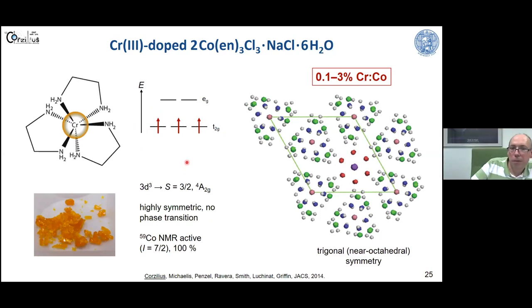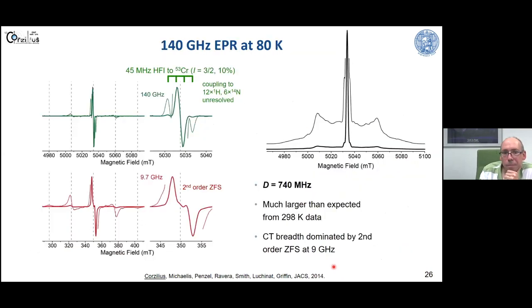And due to the significant ligand field, the excitation energy into an excited state is rather large. So we have a more or less isotropic g factor. However, we have a small deviation of octahedral symmetry into a trigonal distortion. This introduces some zero-field splitting, because zero-field splitting is really sensitive. Even without strong spin-orbit coupling, we have this kind of sensor of local symmetry given by the zero-field splitting in these high-spin systems.